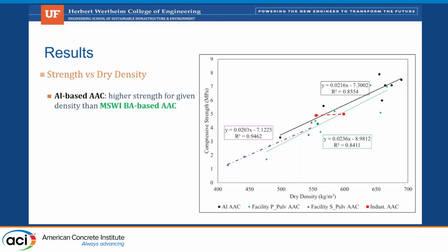If we look at our red line, there's a lot of data on here. The red line is basically what we have at the facility that they gave us, and we try to do our best to match that line. We can produce pretty good AAC using the MSWI ash, and we're working with manufacturers to try and bring that online, but again, we do run into the variability issue. How variable is your ash? If it's giving us an aluminum content that changes even slightly, it's a big deal to them. So I don't think this is quite ready for real time.